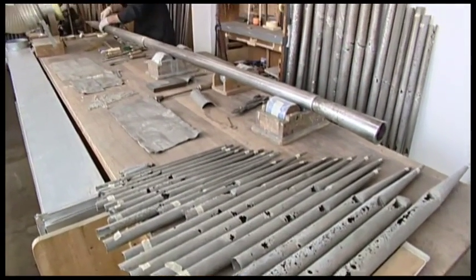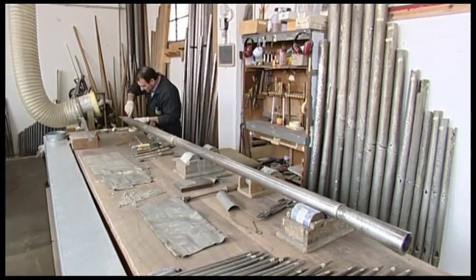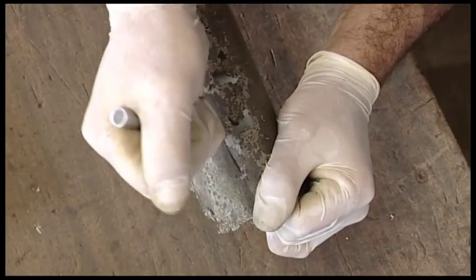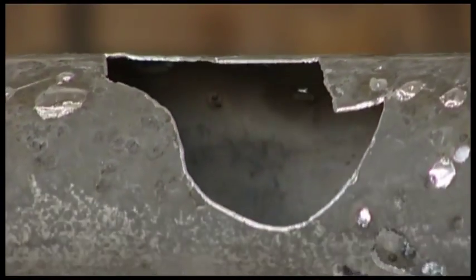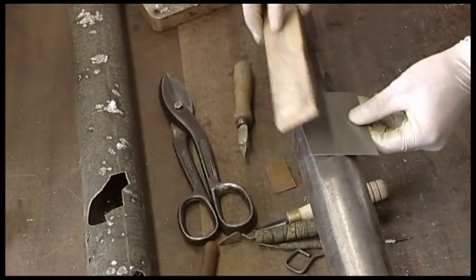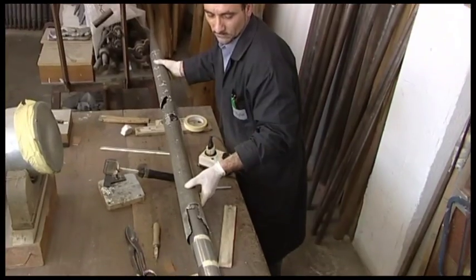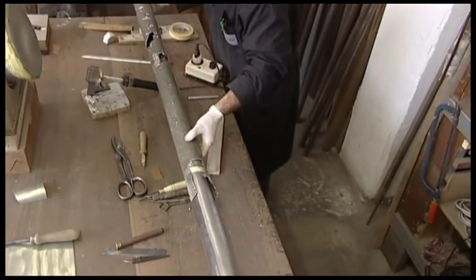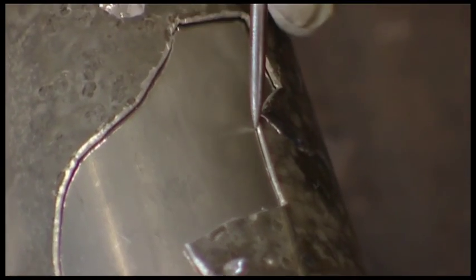The metal pipes in the facade have survived, but their decay is extensive. Uneven edges of heavily corroded sections are cut cleanly away. Newly cast metal of the same alloy composition is prepared. Testing at the University of Bologna has determined the metal composition of these pipes to be mostly tin, with a small percentage of lead and traces of copper.